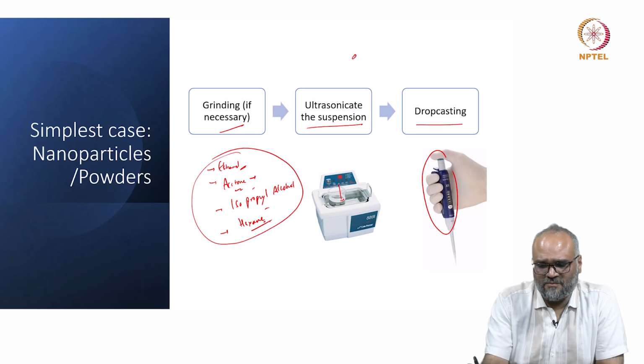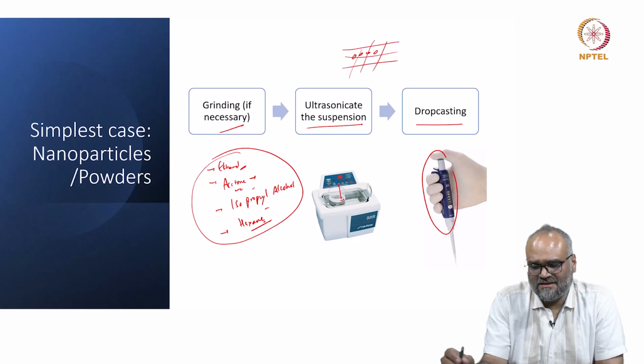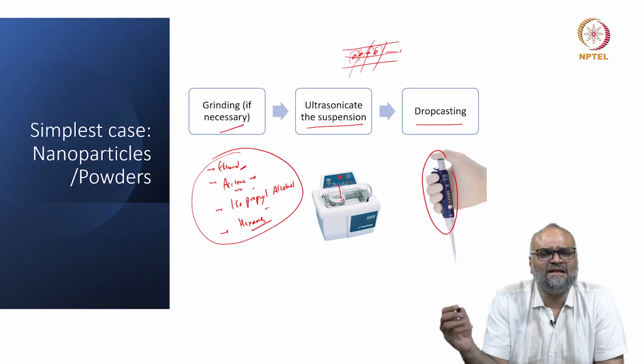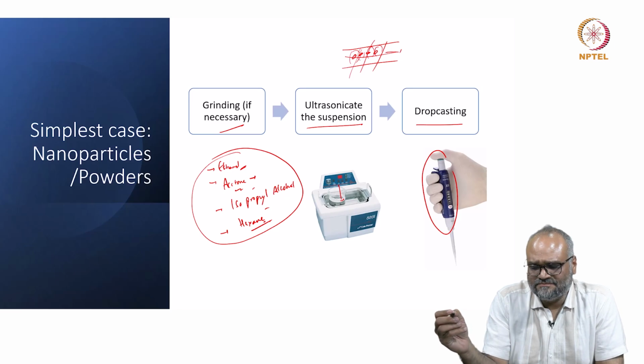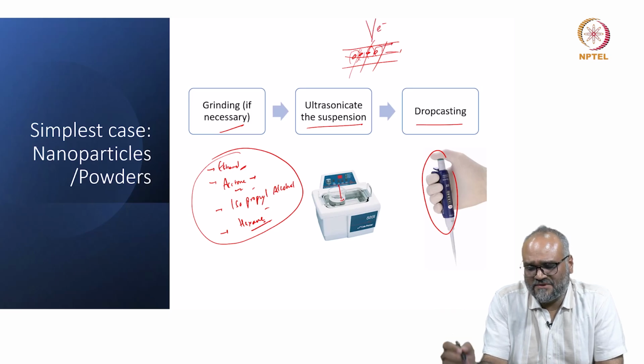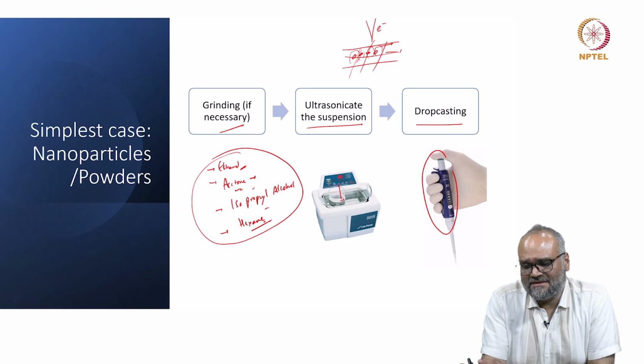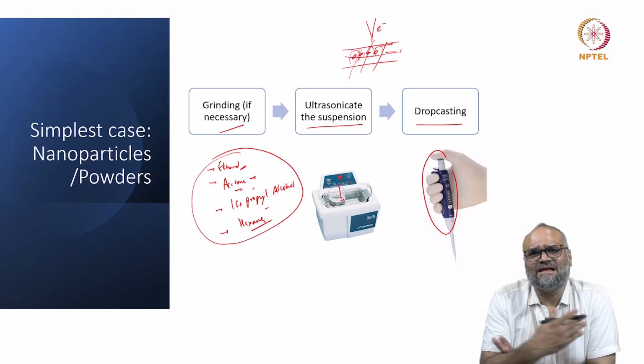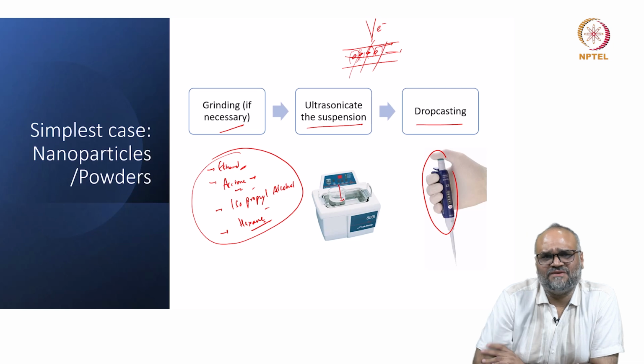So, if I have powder particles lying on a grid, with a monolayer of any of these organic residues on this grid, under an electron beam you would have cracking of these hydrocarbons, and typically you are left with a nice carbon layer deposition on the surface.